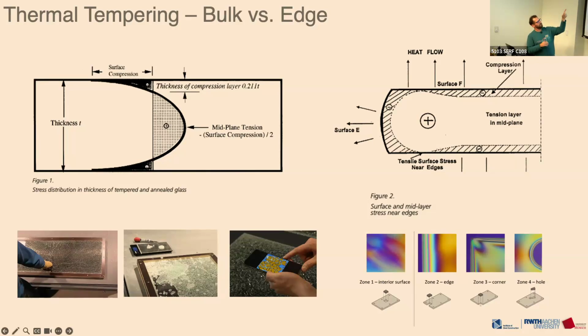Now, that beautiful stress profile with the compressive stress on both sides and this central tension region, when you get to an edge, you likely don't have that beautiful stress profile because you're cooling all around this edge. The edge gets a lot of thermal energy cooling this way, so you tend to get this little keyhole looking thing at the edge of the glass. This happens also in annealed glass. When that glass cools down in automotive, you get a little bit of a tensile region around the perimeter, about 100 millimeters in automotive.